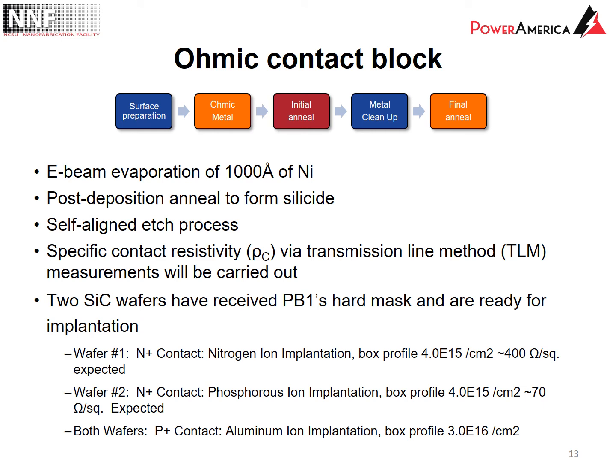The fourth and final process block to look at was the ohmic contact block. And basically what we're doing is forming the ohmic contacts of nickel silicide to silicon carbide. That involves the e-beam evaporation of about 1,000 angstroms of nickel and a post-deposition anneal to form the silicide. And then we can etch away using a wet etch, which will not etch away any of the silicide, so it's essentially a self-aligned etch process. From that point, we'll measure the specific contact resistivity via transmission line method and get the contact resistivity of the